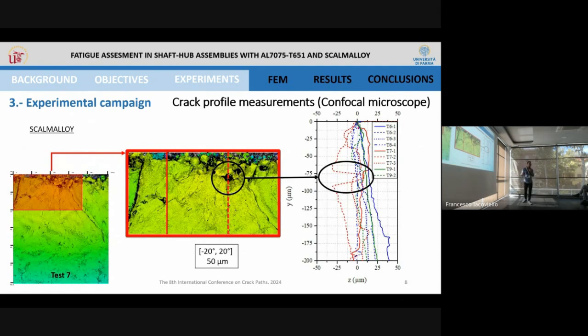Of course, we did the same procedure with the Scalmalloy specimens. In this case, we have to be careful because, as you can see here, these are a lot of measurements of the profile for 3 different specimens, and several measurements for each specimen. More or less, all of them have the same slope, but one of them grows, or seems to grow, contrary to the direction expected. But this has an explanation.